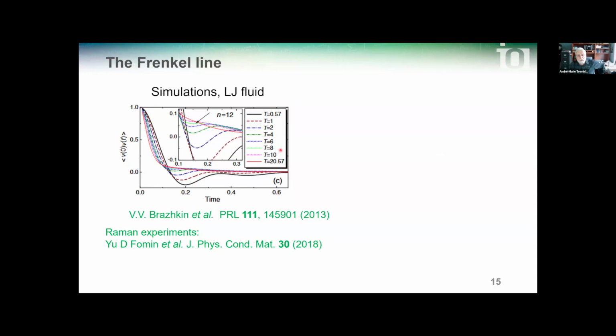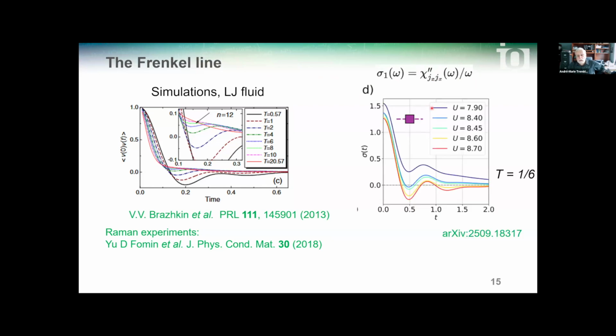In an electronic fluid, a close relative is the Fourier transform of the optical conductivity, which is related to the current correlation function. This is how it looks. As you see, like in the fluid case, that quantity can become negative, like here. In fluids, the Frenkel line is associated to the onset of oscillations instead of just monotonous decay of the velocity correlation function.